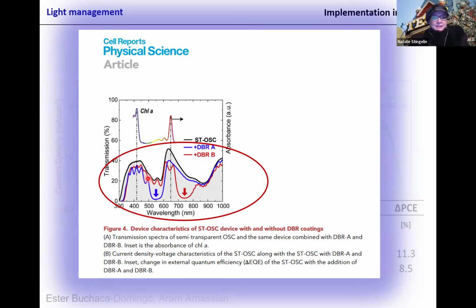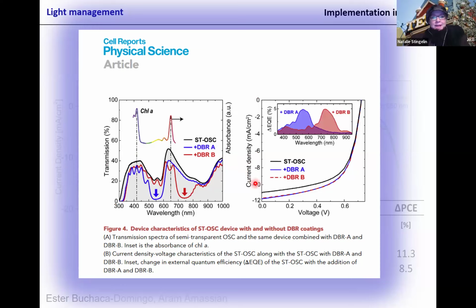Then we make the solar cell, as mentioned in black, just a solar cell without mirror, relatively high transmission where the chlorophyll absorbs. Then we add mirrors in blue and red, which are also relatively open where the chlorophyll absorbs, but they shoot back light that the chlorophyll doesn't need. And by now, you know how solar cells work. Again, current density versus voltage. And you see here we have now a pretty big increase in the short circuit current, so the current at 0 voltage, just because we added mirrors.